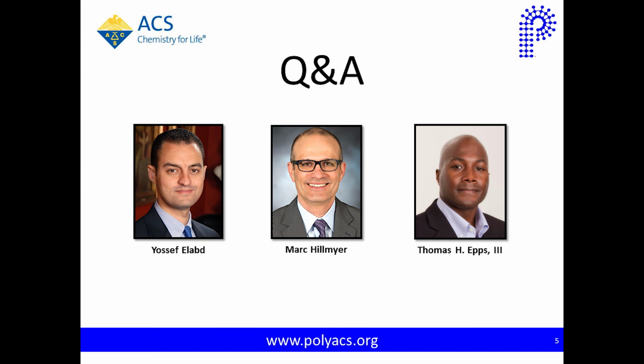And what we found with the polymerized ionic liquids in particular is that the parameters you can regress from that model show that they have a higher free volume than many typical polymers that you would see out there. And there's quite a bit of literature now showing that the reason they have higher conductivities at low temperatures compared to other ion-containing polymers is that high free volume.